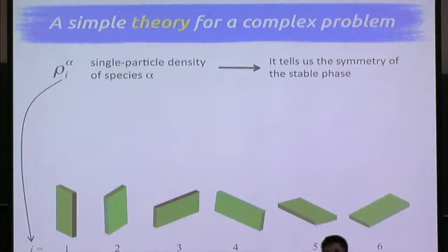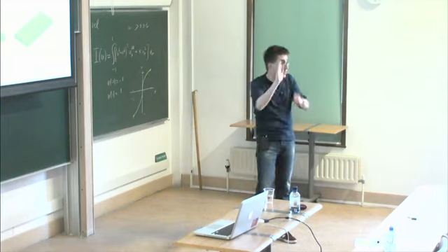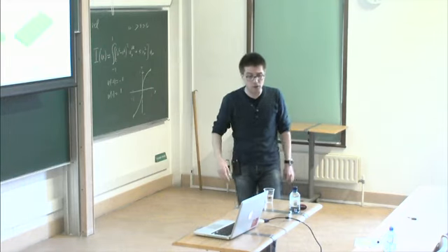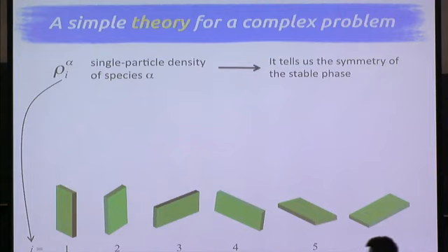So first of all, why am I saying orientation I? Because we introduce an approximation, the so-called Zwanzig model, a restricted orientation model, in which we impose the board-like particles not to take any possible orientation in space. If my hand is a board-like particle, it can't take any arbitrary orientation, but only 6. The 6 orientations in which the axes of the particles are aligned along the axes of a Cartesian reference frame. This simplifies a lot the calculation of the interactions.